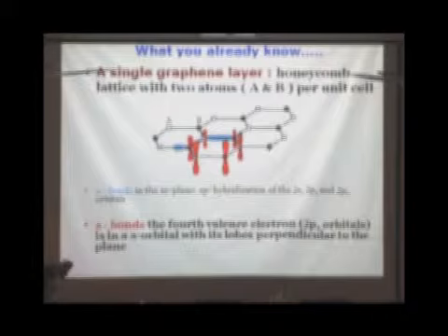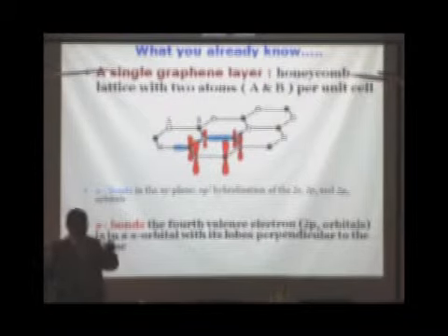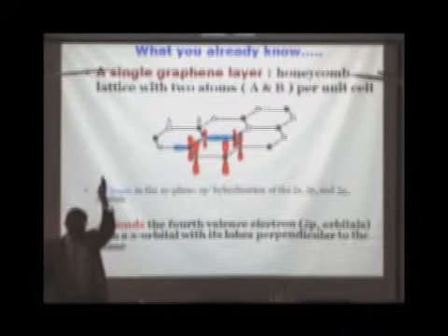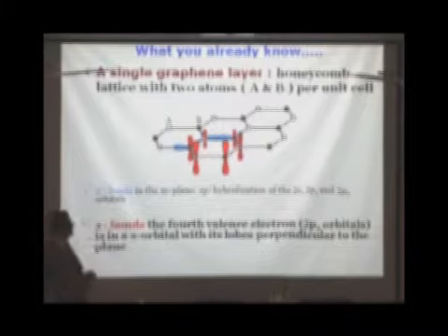So you have two atoms per unit cell, A and B. They are the same carbon, but they form a unit cell. So what you have is sp2 hybridization, and you form the sigma bond. What is of interest for all the key properties are the pz orbitals of carbon, which are the pi electrons. So now you can look at the band structure, what is their energy-momentum relationship, which was done way back in 1948. And it was shown, without going into details,